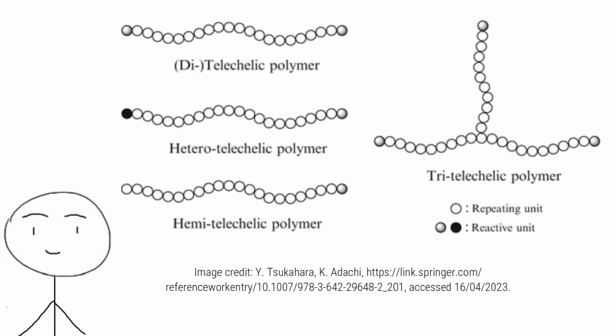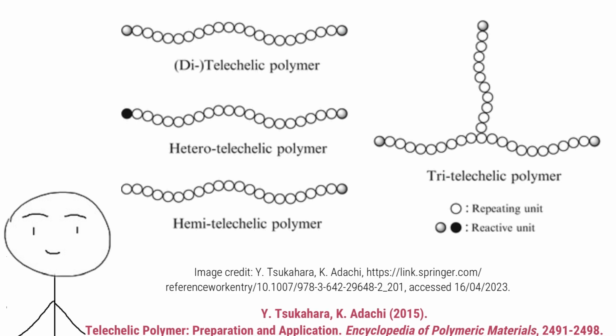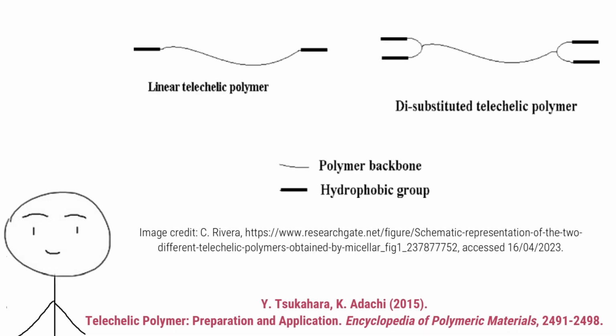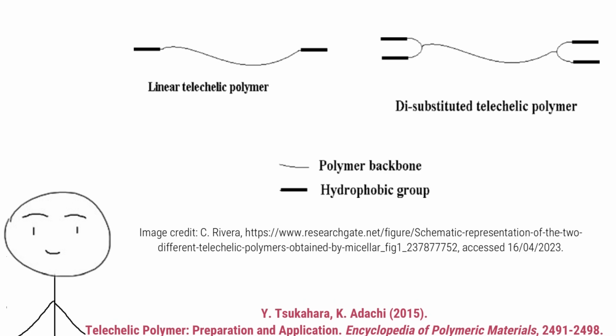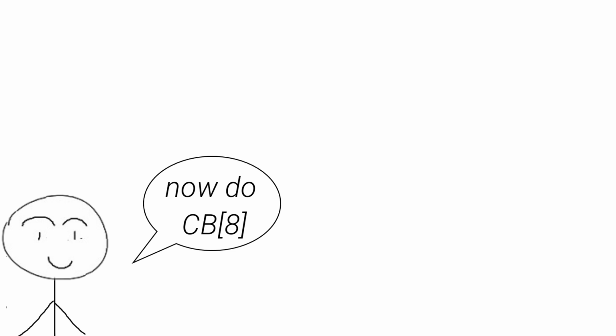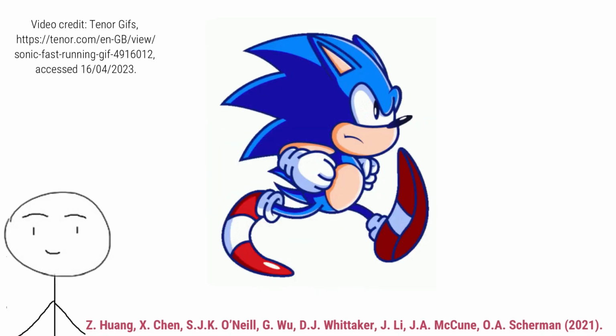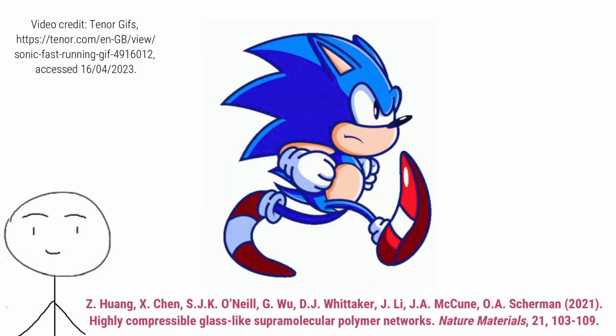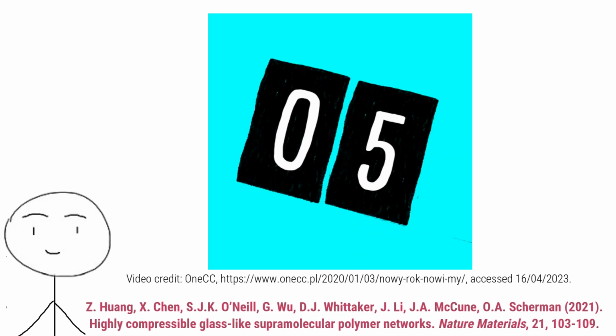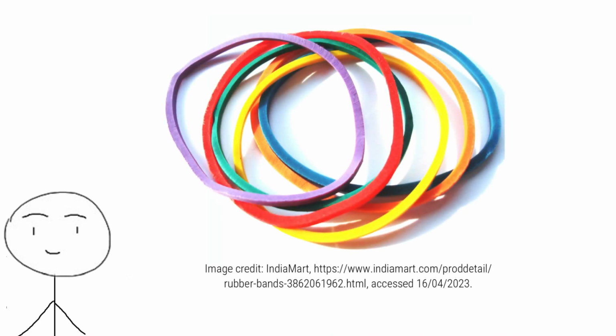Telechelic polymers, or oligomers, are polymers with reactive functional groups at the ends of polymer chains. Importantly, these groups don't come from the original monomers, but instead they've been introduced to the chains for further reactions. Yes, Jim, I'm getting to it. The issue is that their dissociation kinetics need to be fast for self-healing, i.e. the dissociation constant Kd needs to be greater than 10 seconds to the -1, and this gives rise to rubbery properties. Obviously not ideal as a replacement for glass in phone screens.